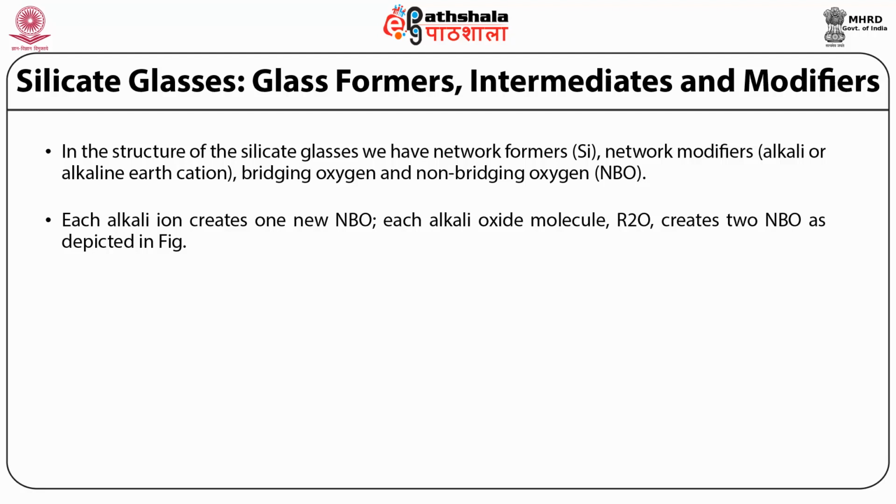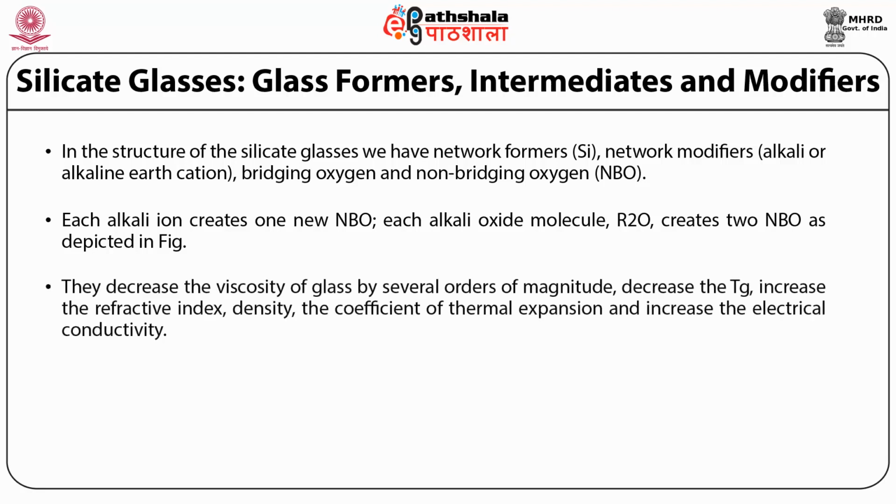Therefore, the alkalis are fluxes. They decrease the viscosity of glass by several orders of magnitude and decrease the value of Tg. They increase the refractive index, density, the coefficient of thermal expansion, and the electrical conductivity.